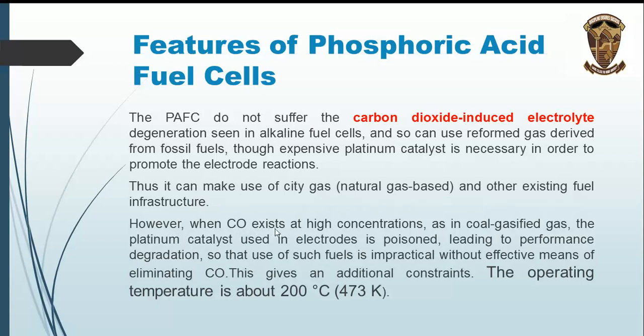However, when carbon monoxide exists at high concentrations, as in coal gasified gas, the platinum catalyst used in the electrodes is poisoned, leading to performance degradation, making use of such fuels impractical without effective means of eliminating carbon monoxide. This gives an additional constraint. The operating temperature is about 200 degrees Celsius, approximately 473 Kelvin.